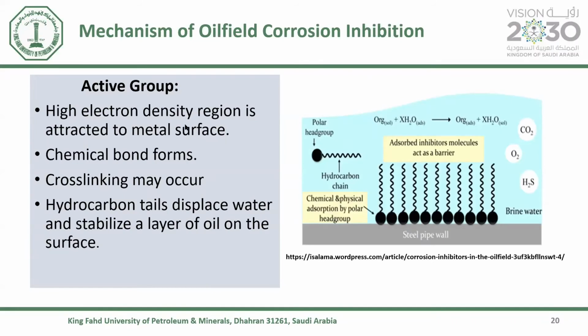So basically, how does corrosion inhibitor work? Normally you have the surface of the pipe, and you have the active group, which is the hydrophilic group that binds to the metal surface. You have a lot of CO2, water, H2S, and then you have salt, what we call brine water. So what the inhibitor does is use the active head to displace the water from the surface and attach to the pipe, whereas the hydrophobic group will displace the water and form a thin film on the surface of the metal.